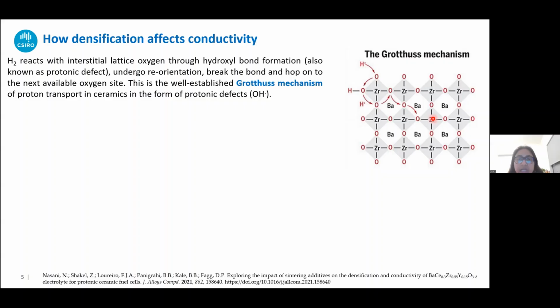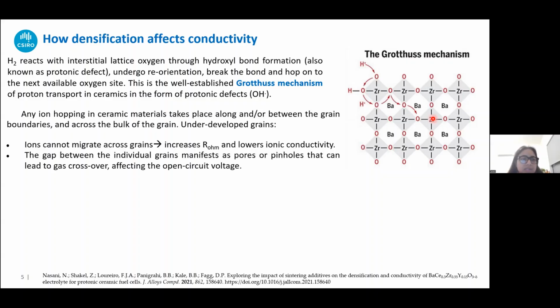Now, in this whole process, whenever any ionic transport is taking place in a ceramic material, it takes place within the bulk of the grain and also across the grain boundary. So from one grain to another across the grain boundary and within the bulk of the grain. Now, if the material is not sufficiently dense, then the grains will also be underdeveloped, and the activation energy is very high, and the ions can't easily migrate from one grain to another. So this basically increases the ohmic resistance, and that drops ionic conductivity.